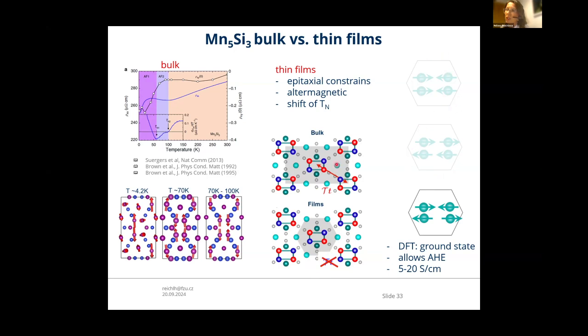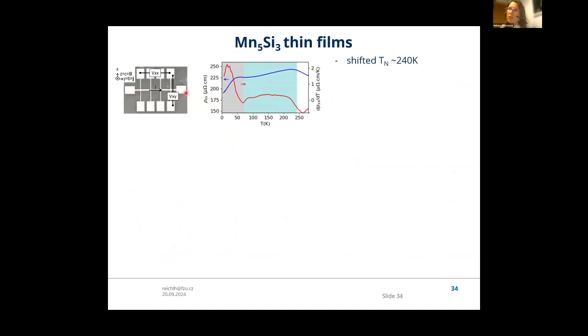Here is just a small cartoon of how the arrows are pointing, which is also supported by DFT calculations showing that this checkerboard ordering is the ground state. So having this experimentally checked and theoretically supported, we patterned the Hall bars. And one interesting thing is that the strain not only stabilizes the hexagonal unit cell in the full temperature range, but it also shifts the Néel temperature, which afterwards we found is not so obscure, that it's happening in other materials as well.